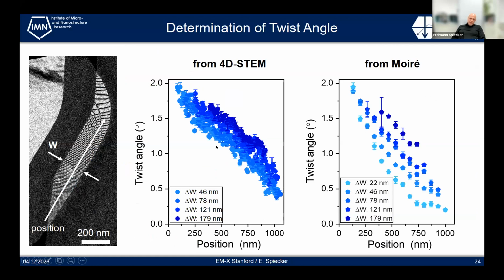So if we do that and apply these 2 techniques, we can determine the twist angle as a function of position from bottom left to top right, and as a function of the width. So for each step of sliding, we evaluate the network, and you saw that with increasing sliding, so to speak, the twist angle also increased. And I want to mention one thing. It would be nice to have a video of that sliding and to see the dislocation actually moving, but this is not possible because it's a stick slip motion. So if you pull on that, then suddenly there's a jump and it slides for a certain distance, then it arrests, and then you have to pull again, and then, like in a stick slip motion, it again slips. So we can only do interrupted sliding, so to speak.